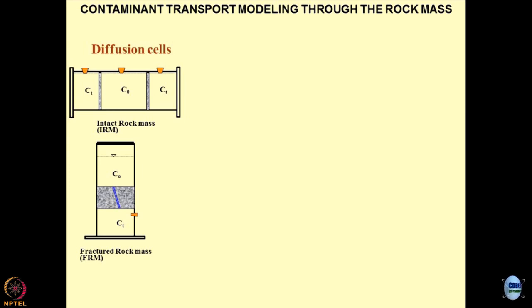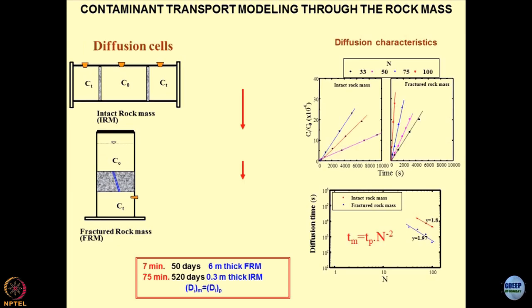Now, I think I am going to answer your question, what you are asking. The setup is ready and then I can record these results, all right. What you will observe here are known as diffusion characteristics. To save our time, we kept both the diffusion cells in the centrifuge and studied them at elevated G value. Though we later realized that the G is not going to influence the diffusion coefficient because this is a molecular diffusion. This paper was read by several reviewers and this is history now anyway. So, what you get is CT by C0 with respect to time, and normally these tests were done for months together, 3 to 4, 5 months, all right,